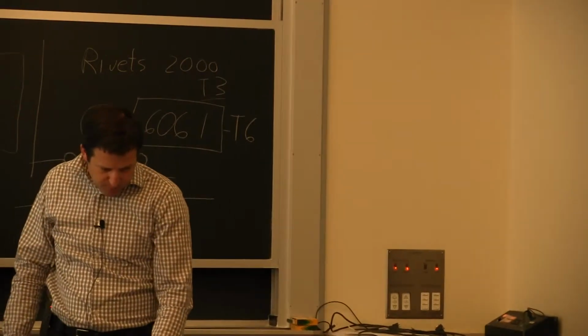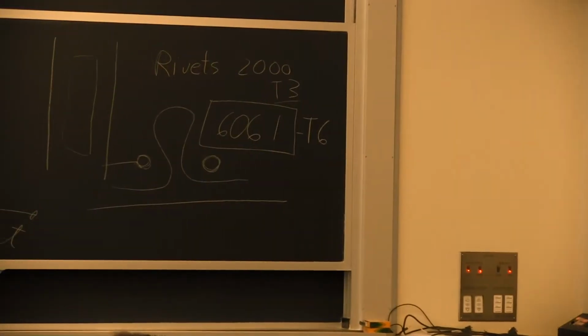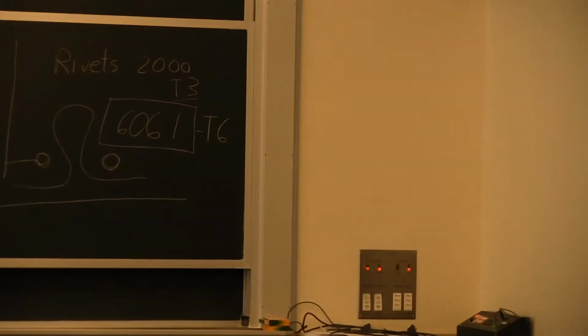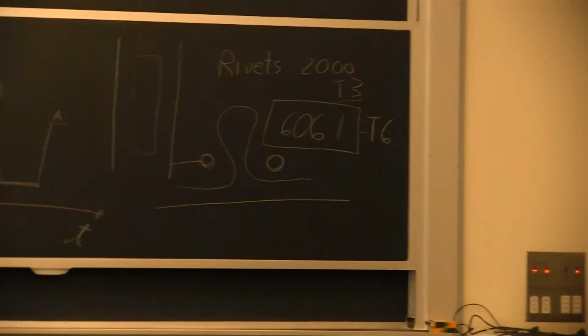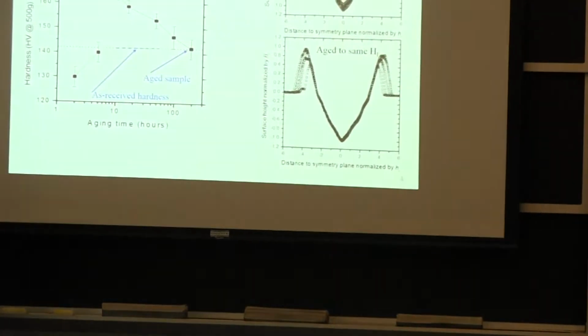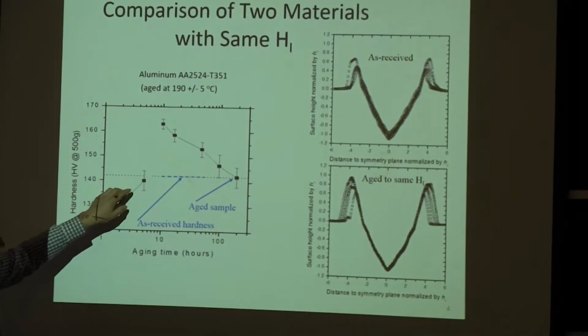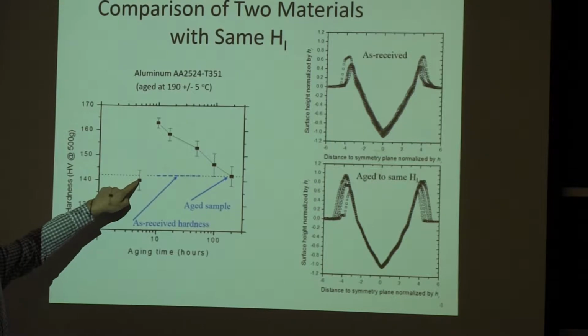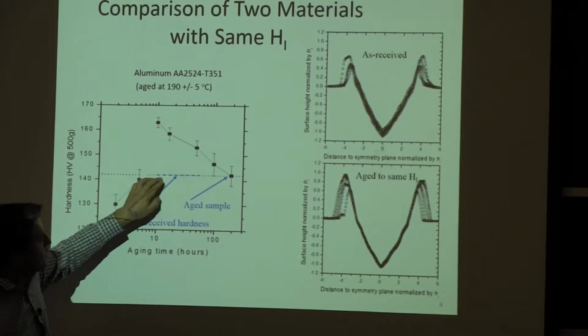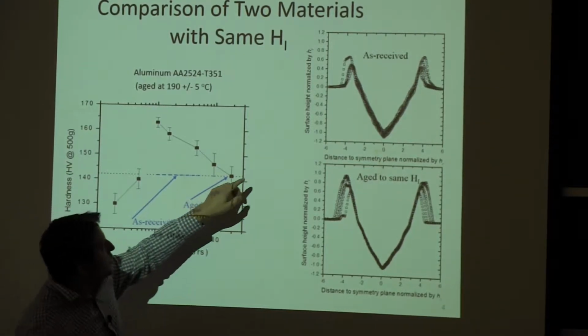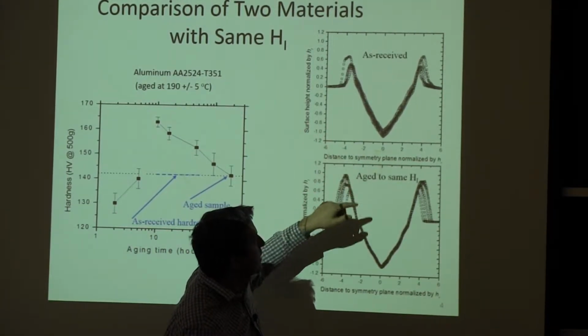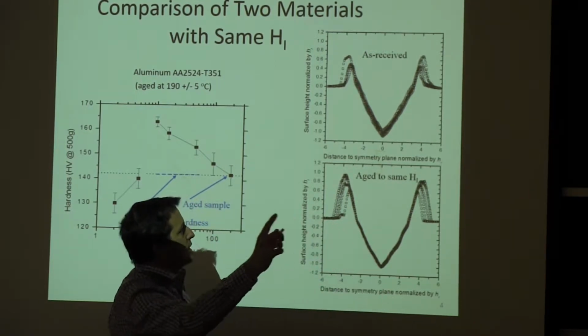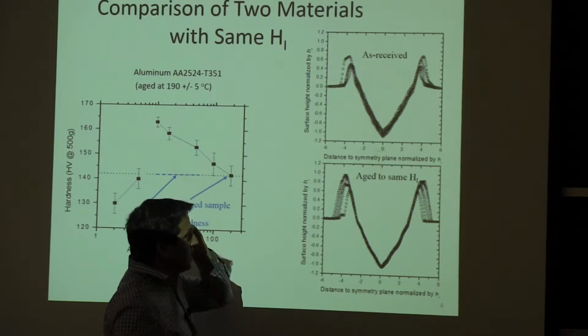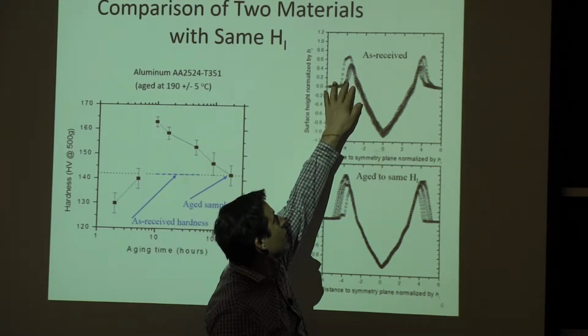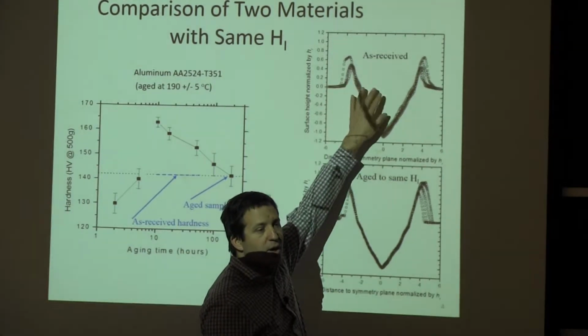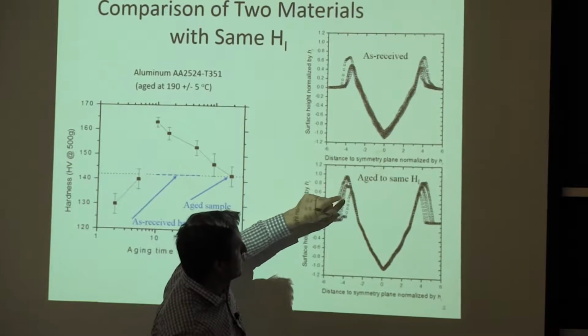The other aspect that I was bringing up, this data here, is just to show that same thing in terms of hardness over time. It's going up, then it's going back down. It's an experiment I did back when I was a graduate student where I compared the underaged configuration, so smaller precipitate, to the larger precipitate here. And what you see in a scratch experiment, where a conical indenter is going in this direction out of plane of the sheet, with the same loading condition, is that you're forming more pileup, more material building up on each side of the scratch in this configuration when it was overaged.